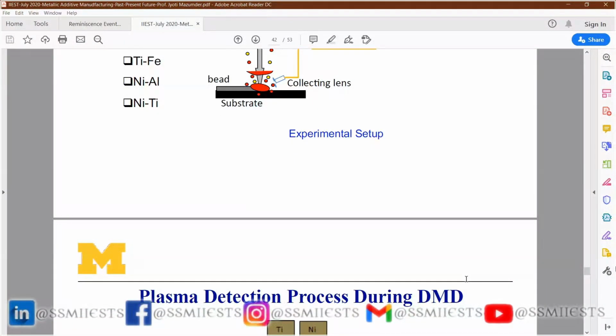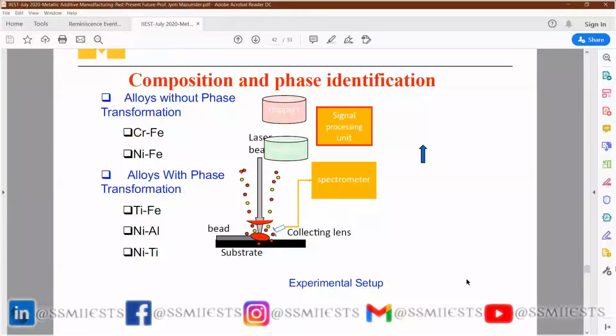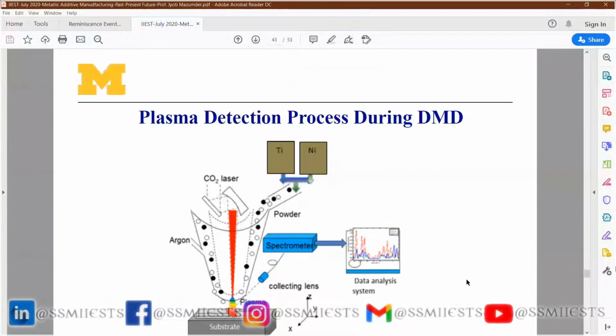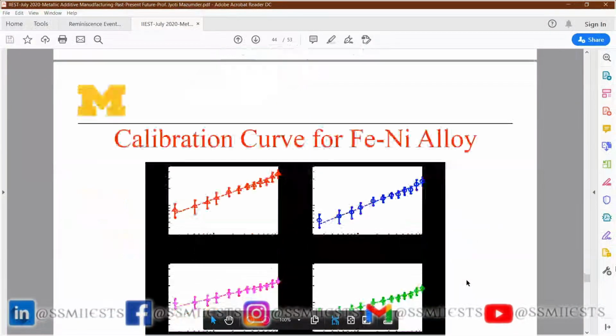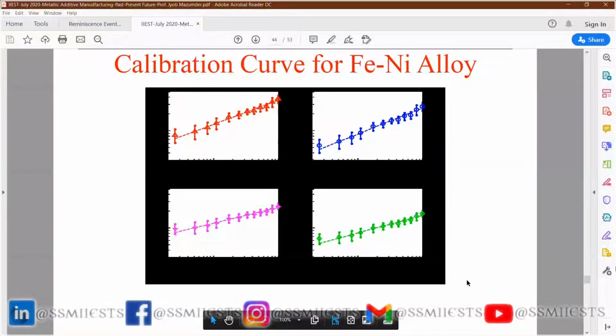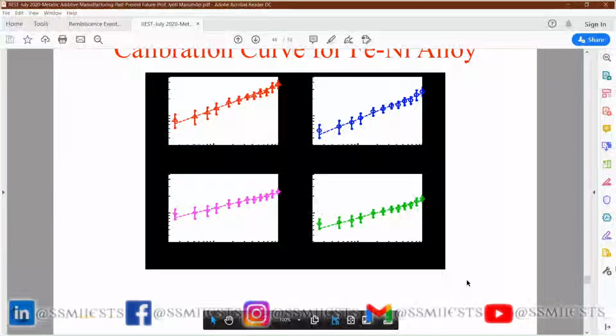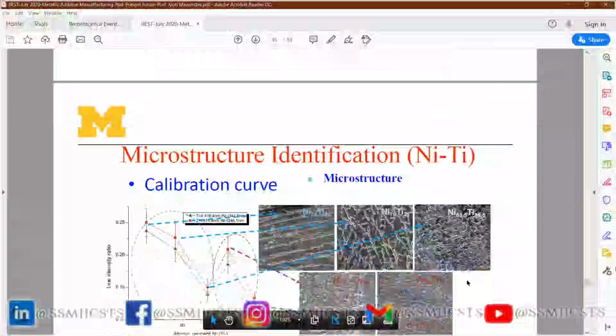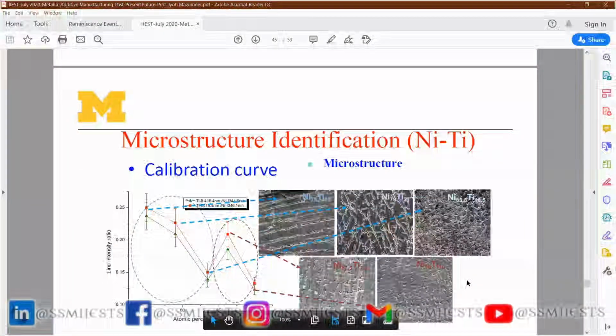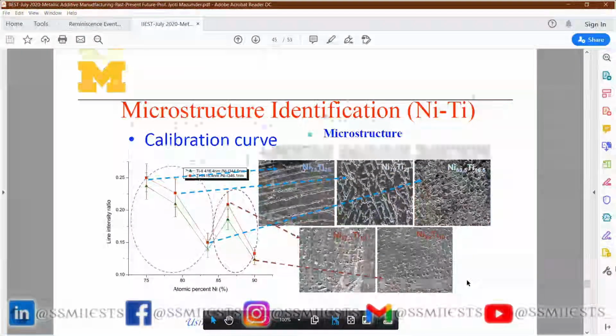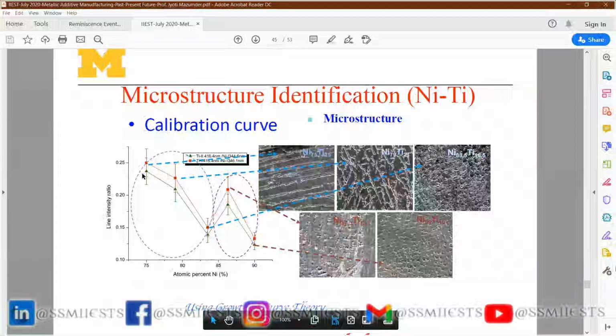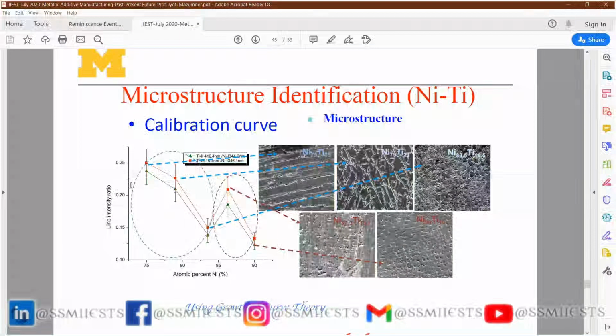But for that, we have to develop a calibration curve for different elements, composition versus the ratios. And you can see, not only do we get the composition, we found using a growth curve theory that as the line intensity ratio changes, the slope changes, and the phase changes too. So not only can we get the composition, we can start to identify the microstructure, all from plasma.